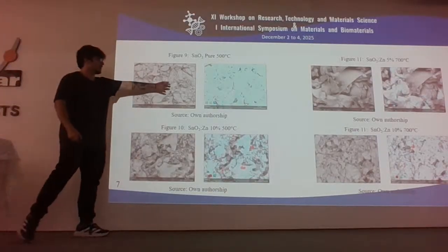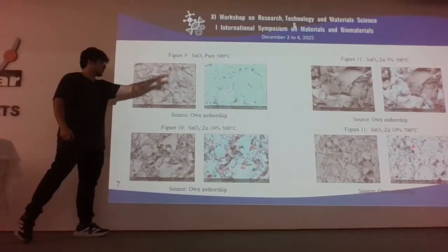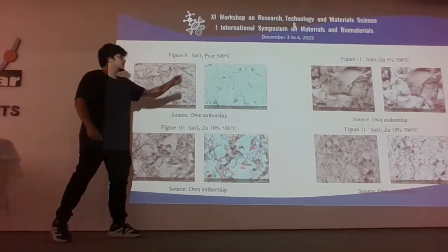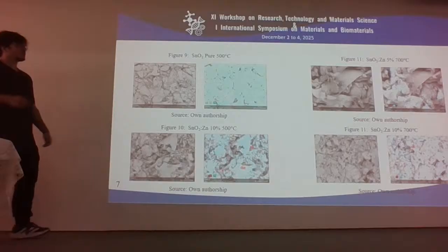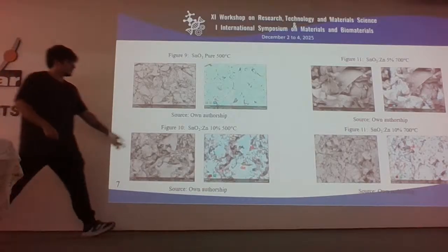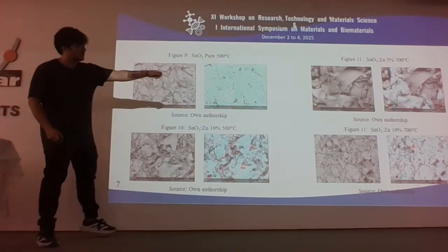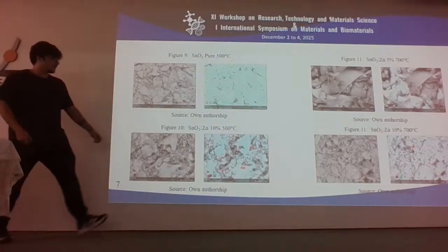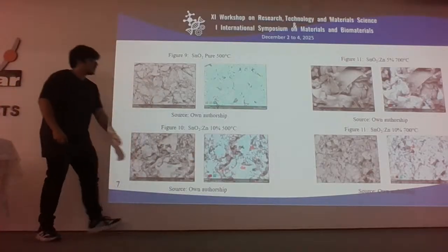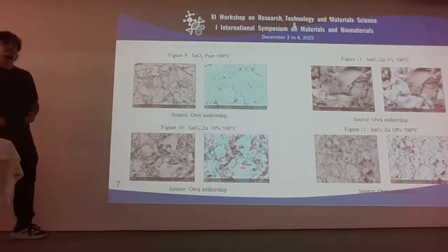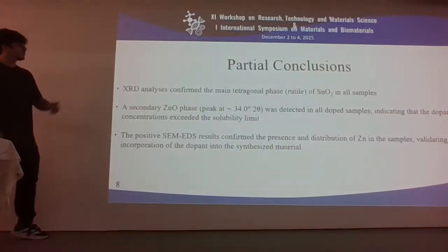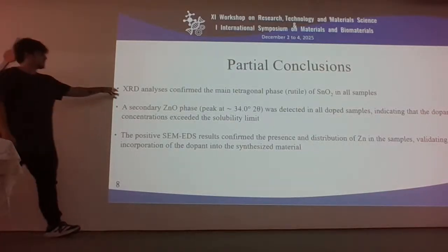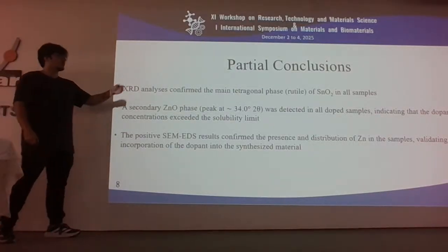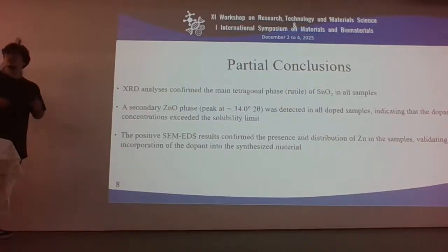So here you have the EDS results. This one is just the base, the SnO2 curve, and these others are with the zinc. So this one is 1%, 5%, and 10%, and these zones in red color are the zones with the zinc dopant.